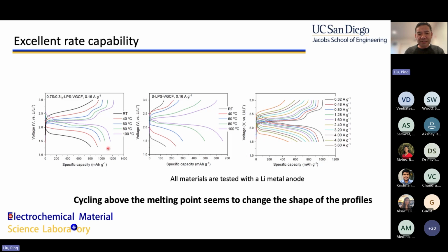We can discharge this material. We almost get a theoretical capacity, and then we can discharge this material at an extraordinary rate. Even at several C, meaning we can discharge these solid state batteries within a few minutes to the order of an hour. The high rate performance is usually a major issue with solid state batteries. But now we have what we think is an inherently more conducting material.